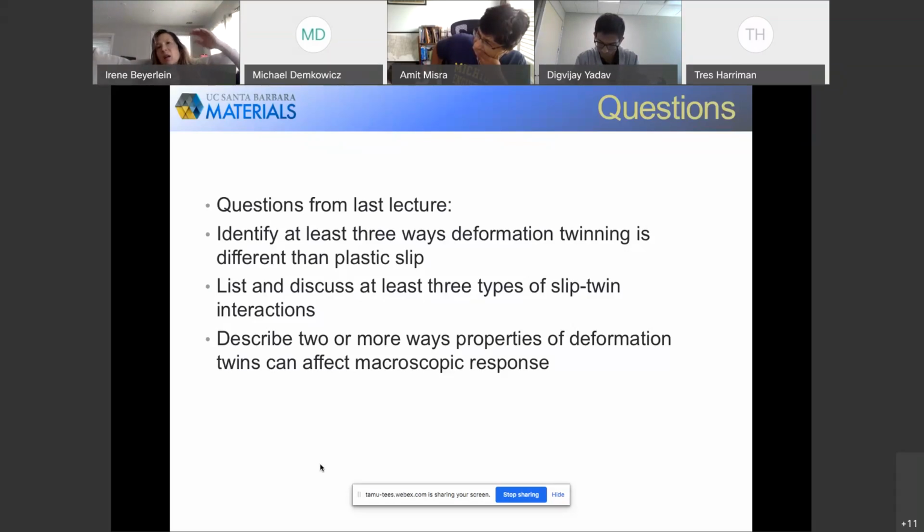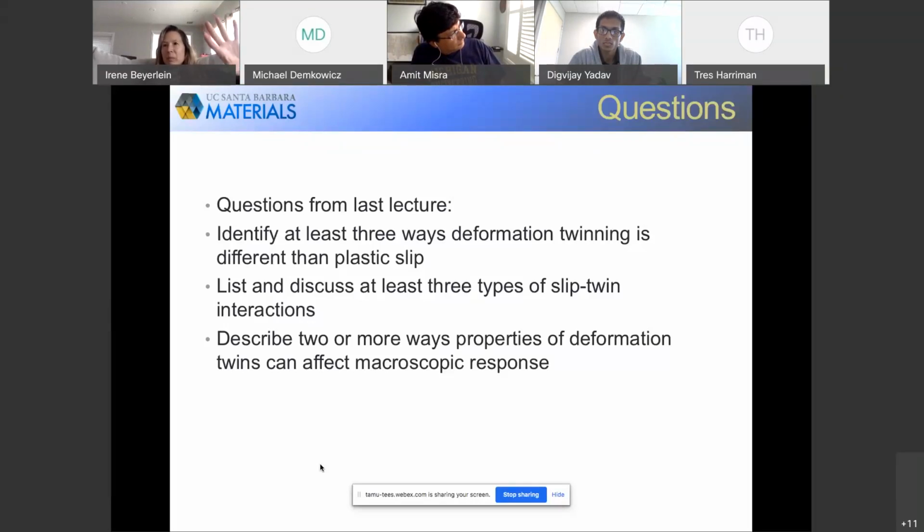So there's the A slip and C slip, and because of the atomic arrangements and density differences between A slip and C slip, accommodating slip modes like C plus A are necessarily harder. So it's easy to make the conclusion that twinning could possibly lie between basal or prismatic A slip and, let's say, pyramidal slip. Now, that's not true for all HCP metals.